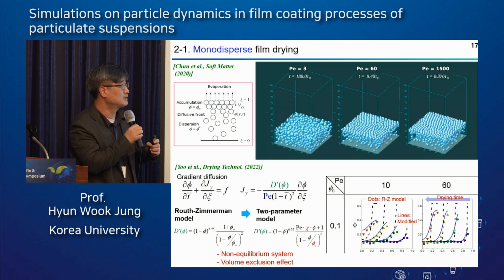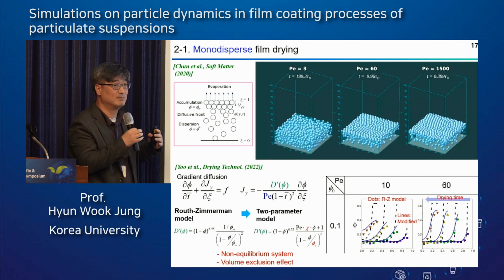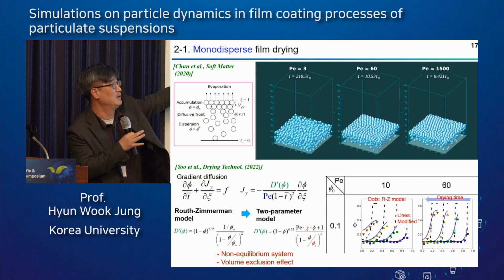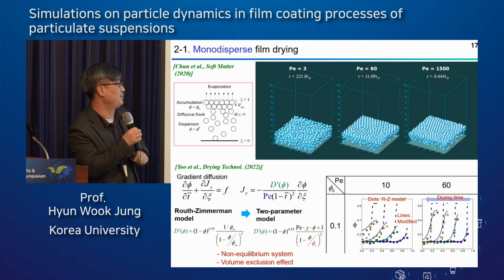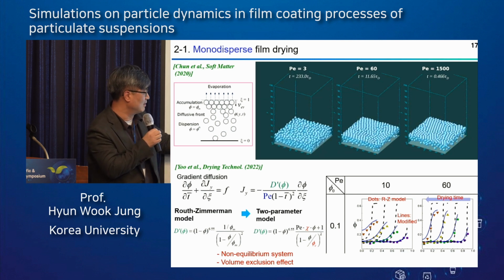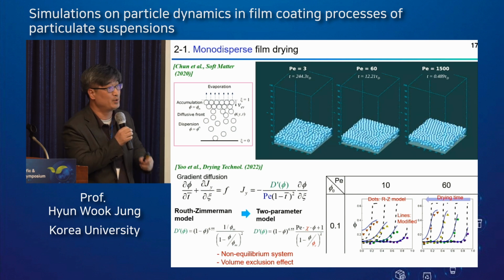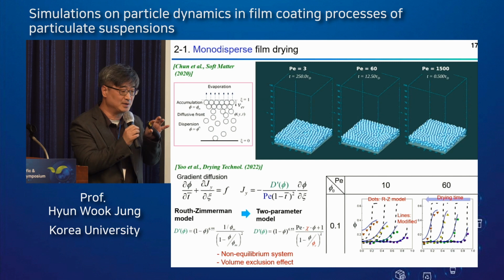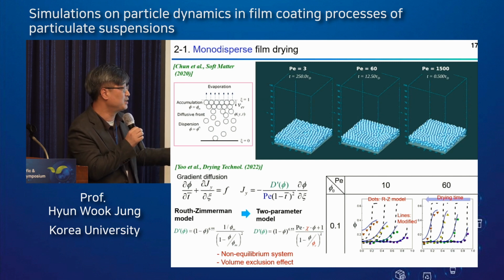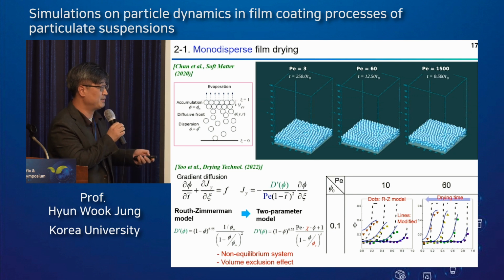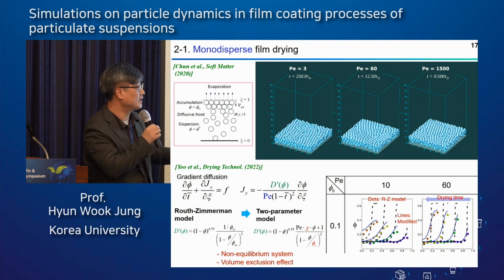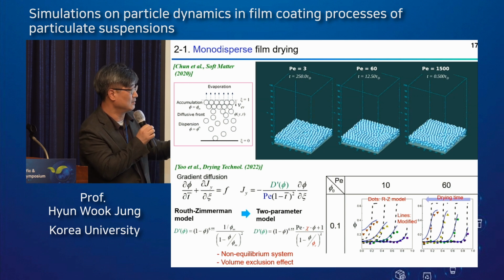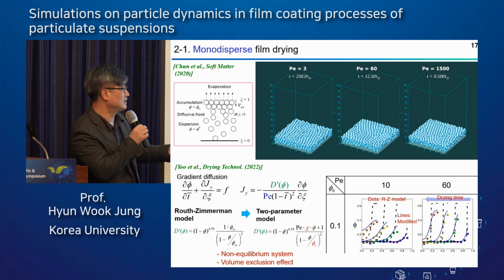Also, we developed a continuum-based drying model to interpret that behavior. A well-known drying model is the Routh-Zimmerman model. We modified this model by replacing the collective diffusivity term with two parameters. This gives good agreement between the LBM simulation and the modified model in predicting the transient drying dynamics under different concentrations and Peclet numbers.